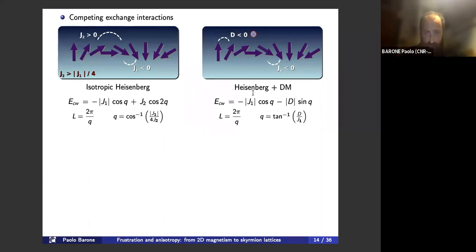So the first is that in the presence of competing isotropic interaction, there is a threshold value. So one needs to have a strong frustration in order to induce a transition from the collinear phase to the non-collinear phase. Whereas in the case of the Dzyaloshinskii-Moriya interaction, in principle, an arbitrarily small value of D would establish a helical phase. And the only thing is that, of course, the periodicity of such a spiral phase would be inversely proportional to the value of the Dzyaloshinskii vector. But there is another important difference.